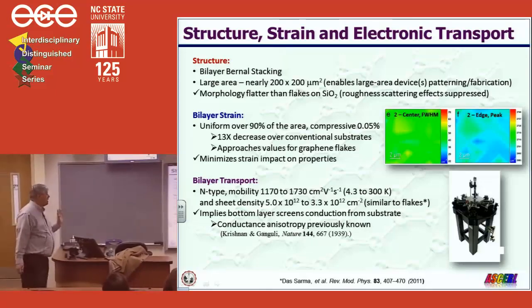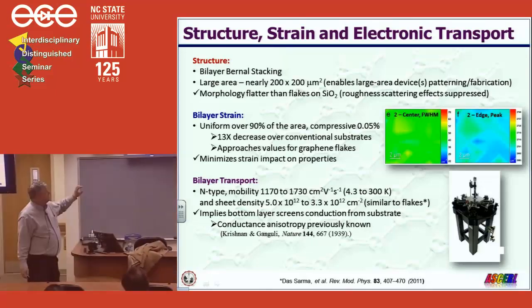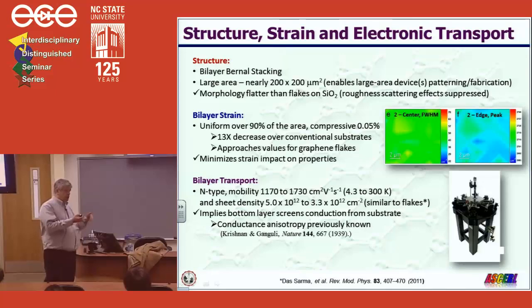And so this is our current area of research, to form these mesas, not only on the silicon face but also the carbon face, do the graphene, and start measuring the properties of the monolayer and the bilayer graphene. Because now we get away from the effects of strain, we get away from the effects of steps and morphological difficulties which have been plaguing us in the past.